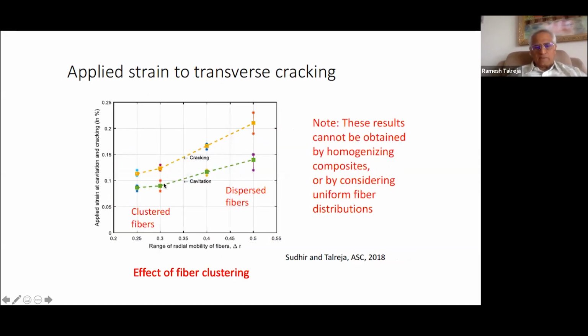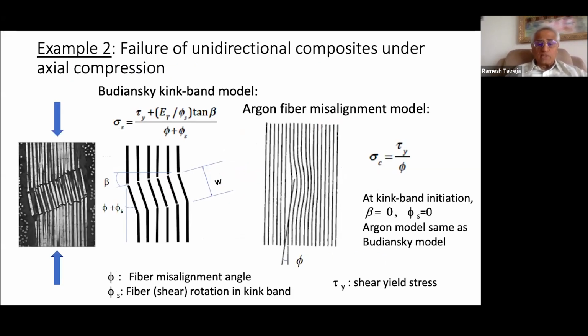Here's another result which presents the same overall result in a different way, where the clustering of the fibers is here rather than the non-uniformity measure. Now it's a clustering of fiber measure. So the more clusters you have, the lower will be the applied strain at which you will cause cavitation. We also did analysis of what happens to crack formation from the cavitation point. Of course, it requires higher strain. So this is an initiation, and that's the progression to crack formation. And you can see that with dispersed fibers, a higher value is needed to cause cracking, while clustered fibers would do that earlier. So hopefully these are good design guidelines for people concerned with manufacturing.